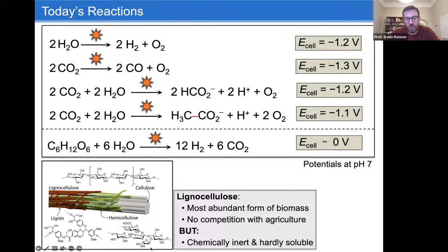And one of the waste substrates we are using is lignocellulose. The structure is shown here on the bottom, where we have a cellulose core that's crystalline. We have the amorphous hemicellulose, and we also have a polyphenolic lignin that's wrapped around to really protect this biomass. And the reason why we are so interested in lignocellulose conversion is that it's the most abundant form of biomass, and equally important, it's not in competition with agriculture. So we cannot eat it, we cannot digest it, and this makes it a true waste product of the agricultural industry. So it's a really good waste product. The challenge, of course, is it's very inert and hardly soluble. So if we think about catalysis with a heterogeneous catalyst or a solar panel, we need ways to pre-solubilize this substrate. And I will mention in a second how we do this.